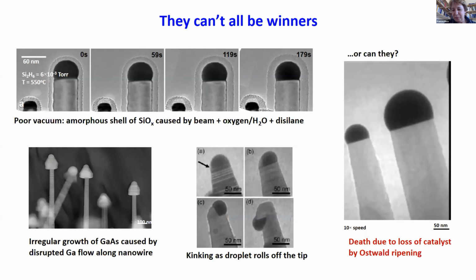So I don't want to leave this topic with the impression that, oh yeah, everything works, you plan it, you set it up, and then it works. There's all kinds of ways that the experiments fail. And so I'm showing a few of them here. If the vacuum is dirty, you get junk all over your sample, you can't grow anything. If the diffusion pathways get messed up, you get these odd shapes that are hard to use or understand. And you can also get kinking, growth instabilities, morphological changes, etc.